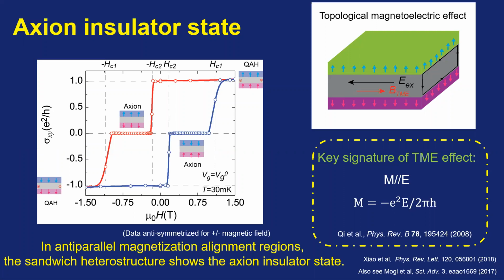So when the field is between HC1 and HC2, there is this kind of anti-parallel alignment. The top surface has e squared over 2h conductance. The bottom surface has minus e squared over 2h conductance. So the total conductance is 0. This kind of state is called the axion insulator state. This axion insulator state is a good platform for the detection of the topological magneto-electrical effect. So we know the magneto-electrical effect. Why we call it topological is just because in this kind of material, the magnetization and the electric polarization are parallel to each other, and the coefficient between them is quantized.